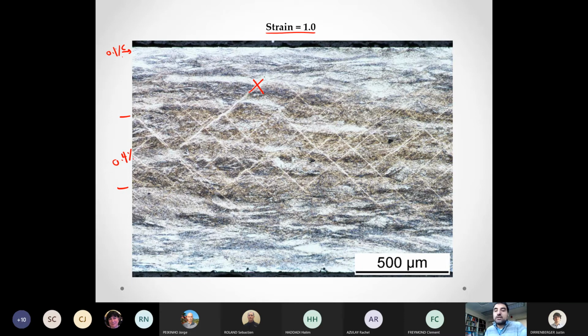And I think that's the main reason why we were able to cold roll the martensite without fracture. In the normal case, these bands would meet the surface, create a crack, and this crack would cause the sample to break. But in this case, the bands are arrested by this softer outer layer, and as a result, we do not have an origin or an initiation site for the crack, and we can continue to deform the martensite without a problem. You can even see some small cracks on the surface here, but these are not dangerous because the outer surface has only 0.1% carbon, and therefore it's a very tough material.